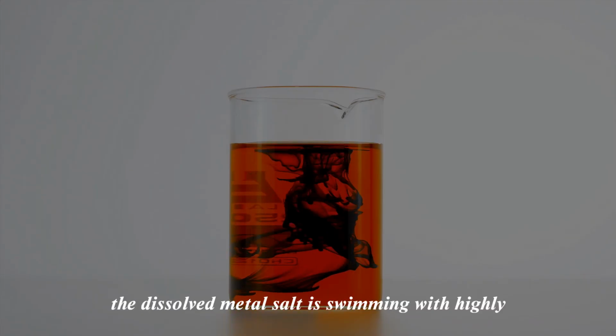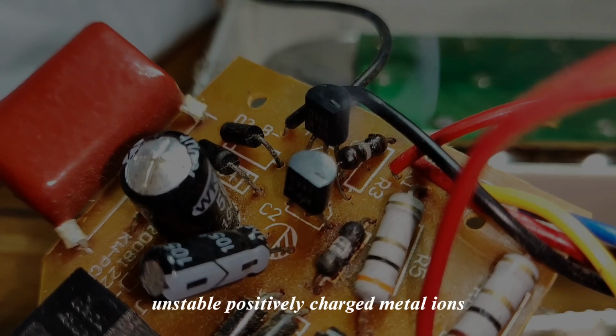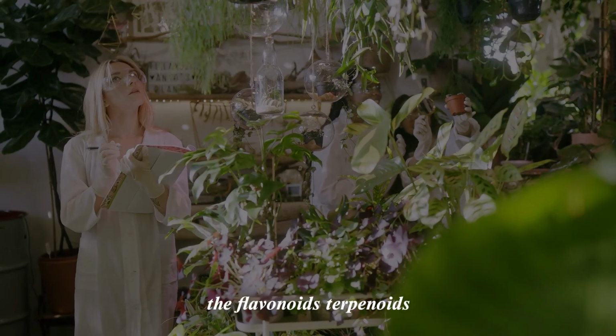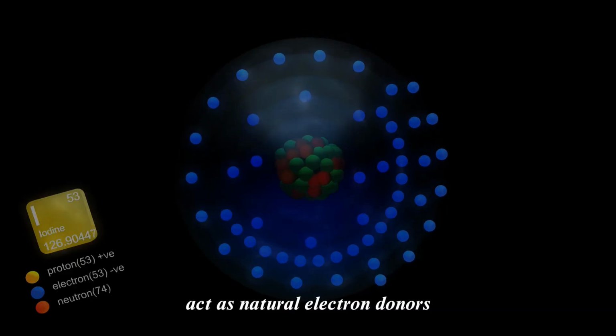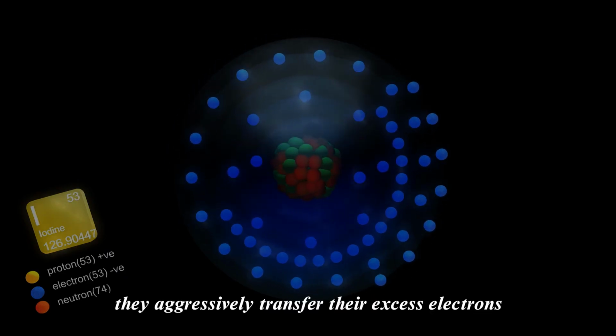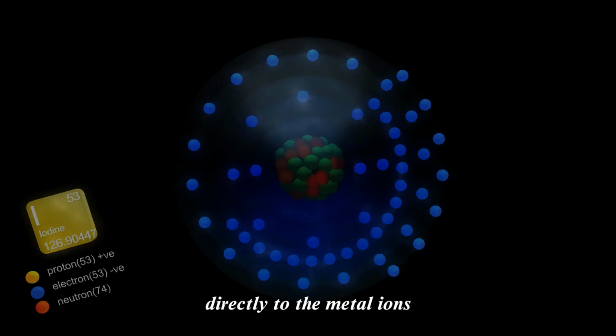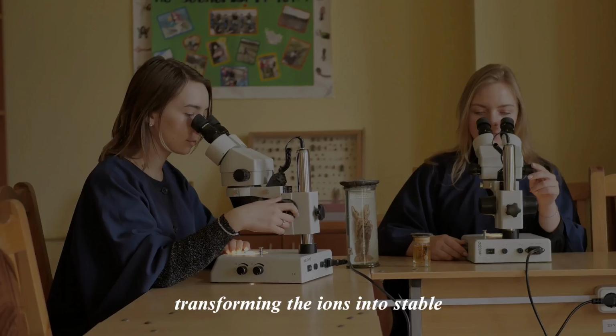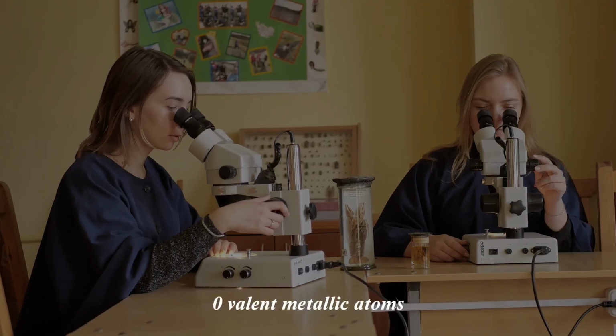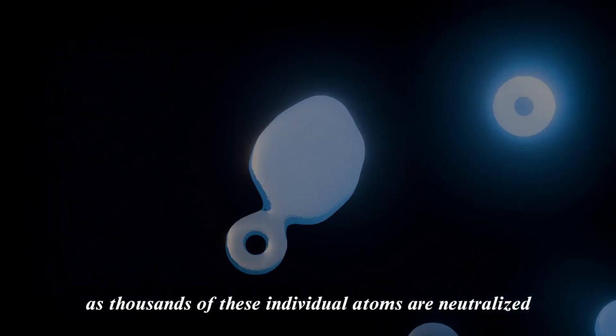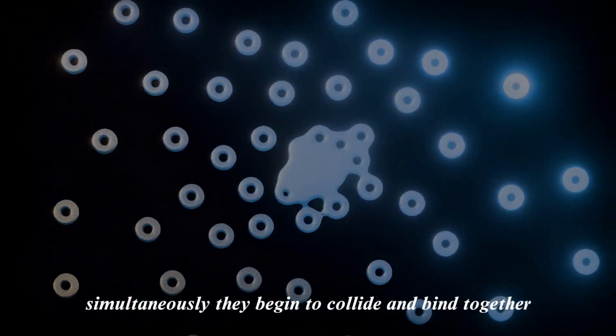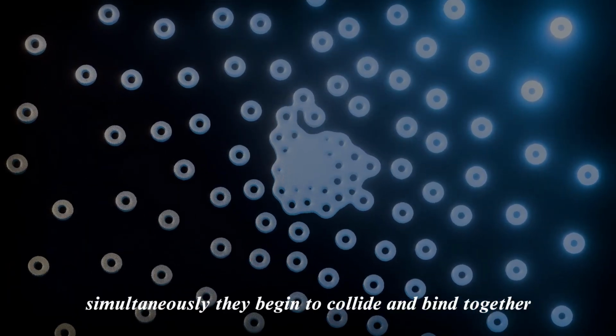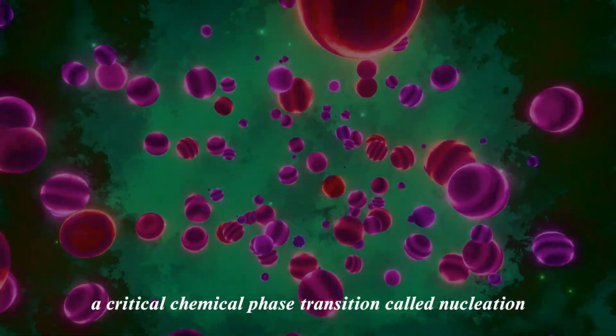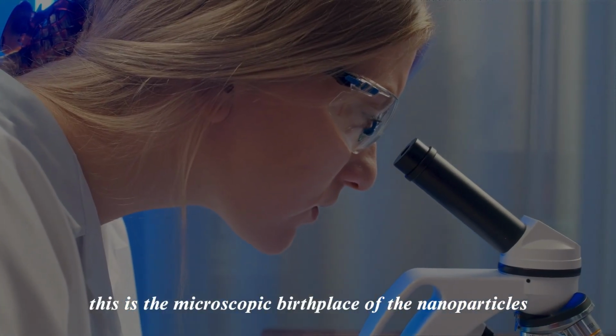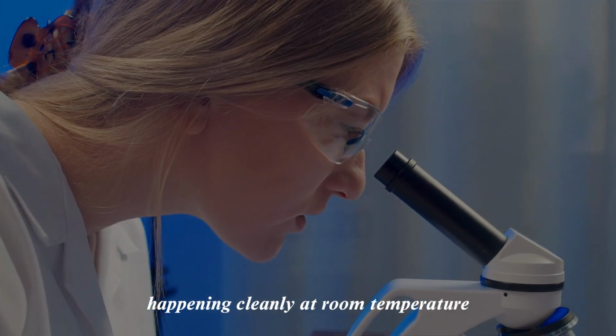The dissolved metal salt is swimming with highly unstable, positively charged metal ions. The flavonoids, terpenoids, and catechins we identified act as natural electron donors. They aggressively transfer their excess electrons directly to the metal ions. This rapid shift neutralizes the electrical charge of the metal, transforming the ions into stable, zero-valent metallic atoms. As thousands of these individual atoms are neutralized simultaneously, they begin to collide and bind together, a critical chemical phase transition called nucleation. This is the microscopic birthplace of the nanoparticles, happening cleanly at room temperature.